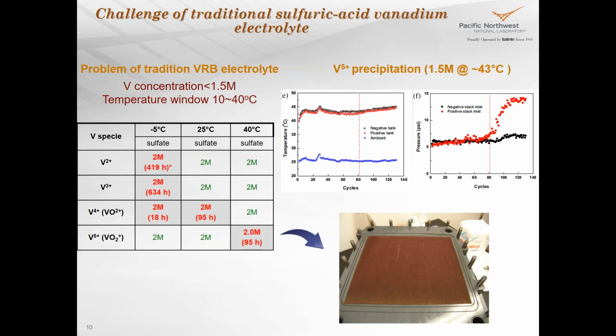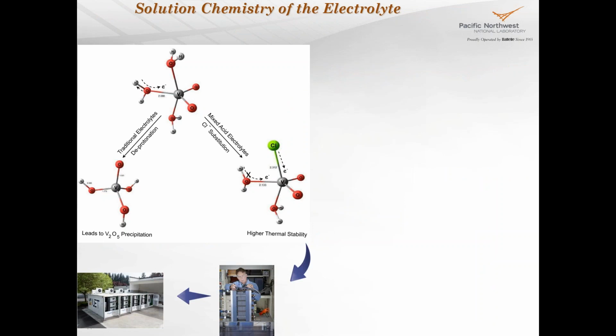So our research started from how we can stabilize this system. And first, we identify what's the reason to cause the vanadium 5 to precipitate out. It turns out it formed V2O5 through a deprotonation process. And then after we understand this, we introduce a chloride ion which can bond with the vanadium to prevent that deprotonation process.